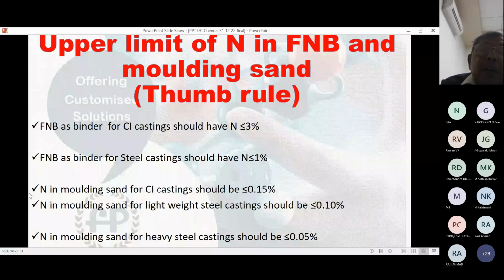It is more appropriate to talk about percentage of nitrogen in molding sand than in binder. So nitrogen in molding sand for cast iron should be less than or equal to 0.15%. That is the value I have copied from this BCIRA, and we have seen many of the foundries using cold box. They test nitrogen to see that this limit is not exceeded. The nitrogen in molding sand for lightweight steel castings should be less than 0.10, and for heavy steel casting it should be less than 0.05%.